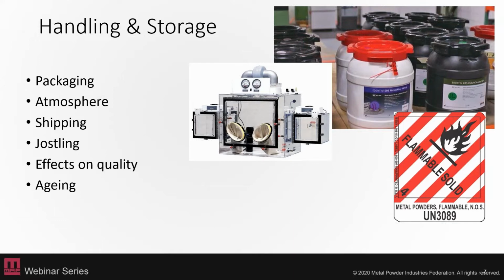And another factor that we recently became aware of at Ames is just even aging of your powders. Some compositions of alloys will just age at room temperature, and so as you're shipping those or as you're storing those, you need to be aware of those compositions that will change with just time at room temperature and under ambient conditions. And so making sure that you're aware of those factors is really important for the particular powders that you're dealing with.